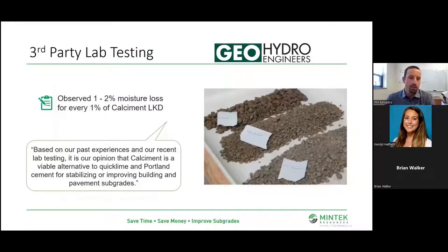And they had some observations there at the end of their study. They observed 1 to 2% moisture loss for every 1% of Calciment LKD, something that we have seen consistently throughout our years using the Calciment product, really good product. And then a nice little quote there from the guys: based on their past experiences and the recent lab testing, it is our opinion that the Calciment is a viable alternative to quicklime and Portland cement for stabilizing or improving building and pavement subgrades. So in line with everything we've been talking about in the 101 and 201 and continuing here in the 301 section.